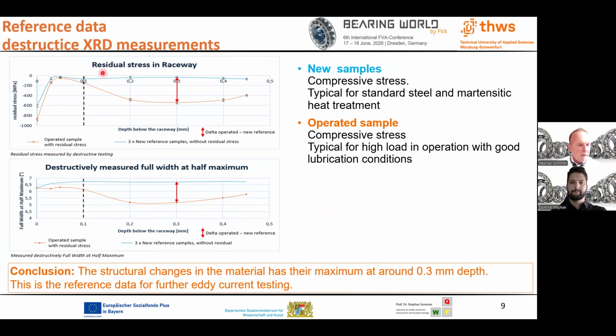You see here residual stress in the raceway, and you see here the full width at half maximum. The blue line shows the new samples. This is a typical residual stress for standard steel and martensitic heat treatment, the new bearings. And here the orange line, these are the operated samples. And this is a typical compressive stress that is typical for high load, but good lubrication.